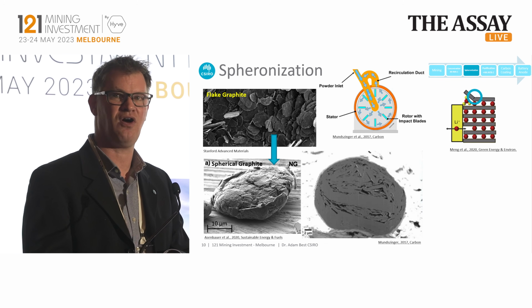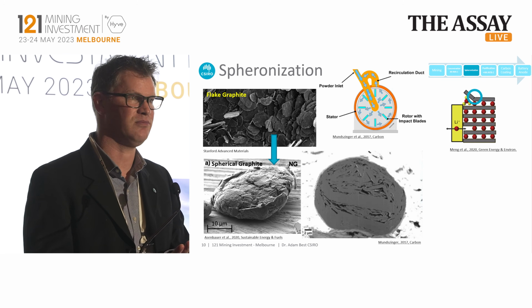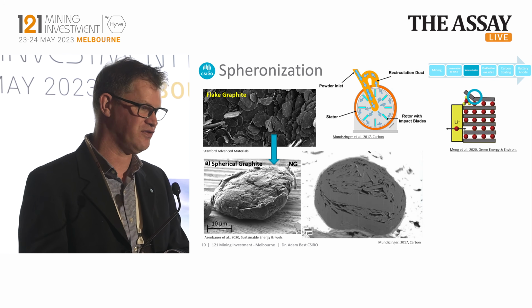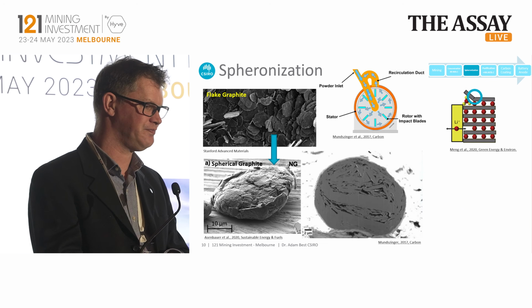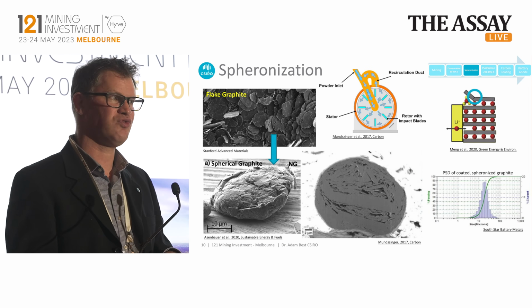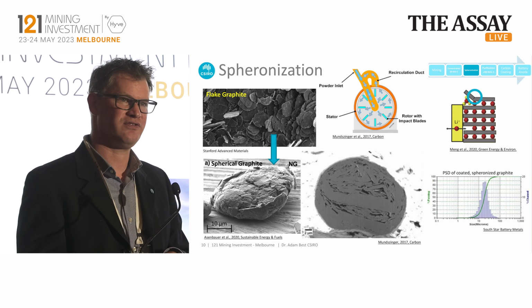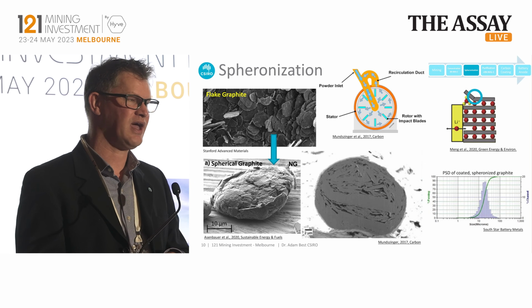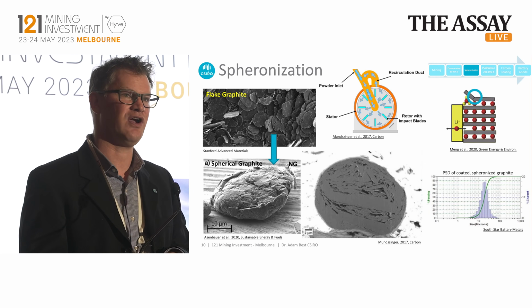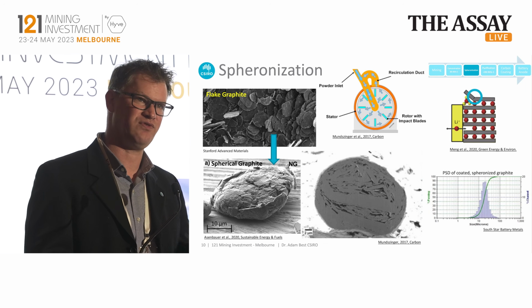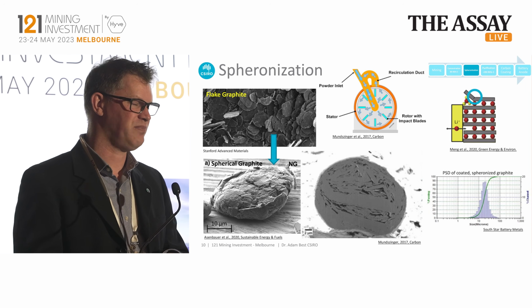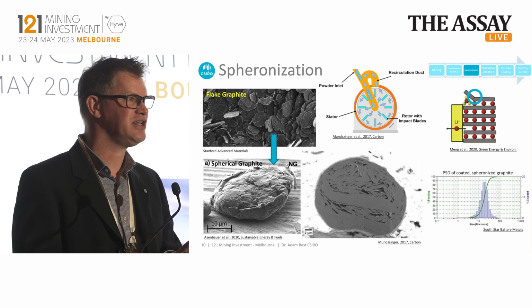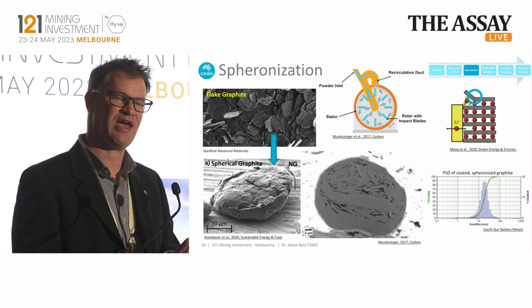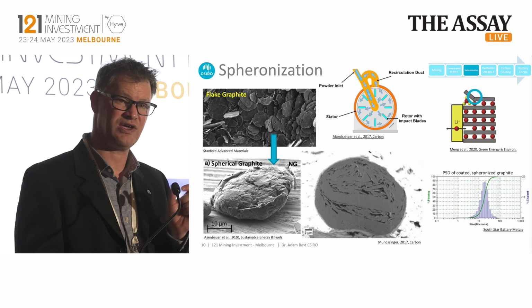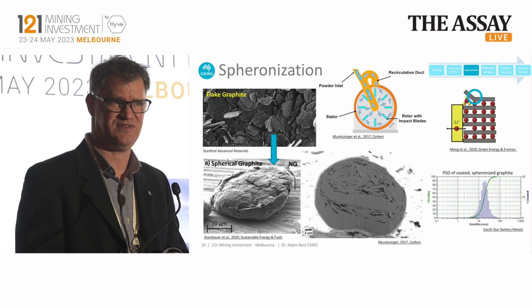And we spend a lot of time working with our customers to maximize and optimize that process before you go to scale up. The last thing that's really important is particle size distribution. So we can't just use everything that comes out of the spheronizer because we get a range of different particle sizes. For most battery companies, they're looking at in an energy cell, they're looking for a particle size of about 15 to 17 micron. They're looking for a really tight, what we call D50.